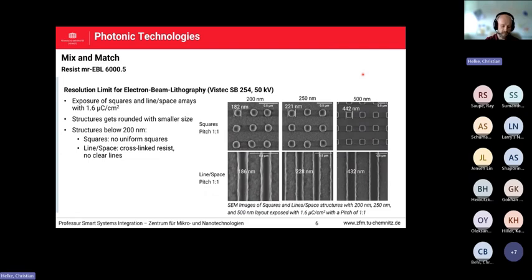First of all, we realized all the experiments for every process, E-beam and I-line stepper, on our, let's say, CD structures itself. We have for our E-beam tool some special structures where we expose lines and dots, and we could resolve here structures down to 200 nanometer with this resist, with a certain exposure dose of 1.6 microcoulomb per square centimeter, which is quite low. It's nearly in the range of the limit of our E-beam tool itself. So it's really a fast photoresist or E-beam resist, let's say this one.